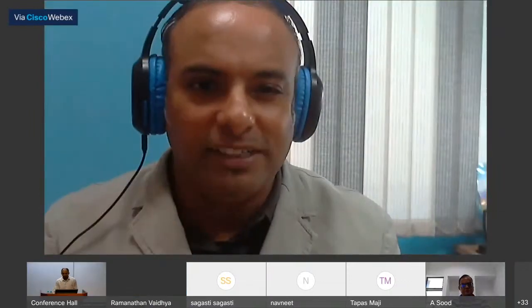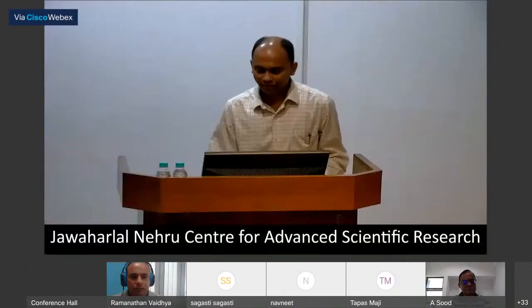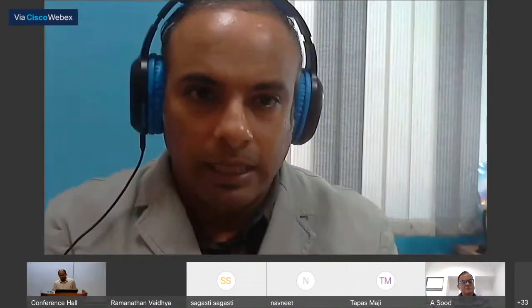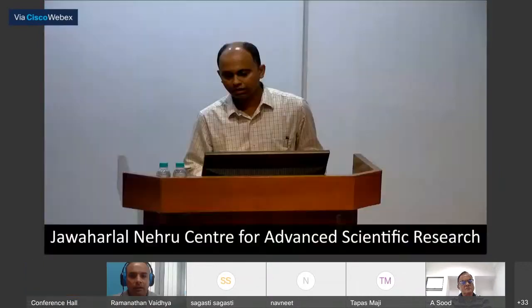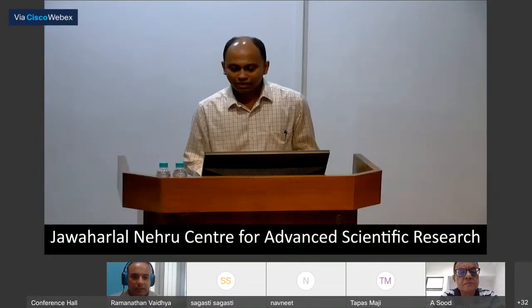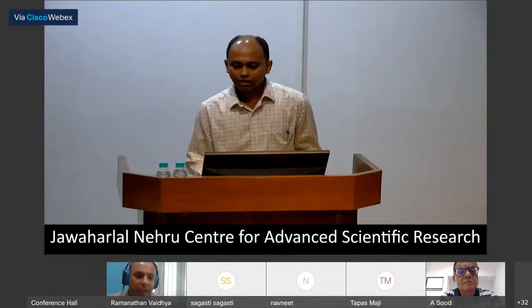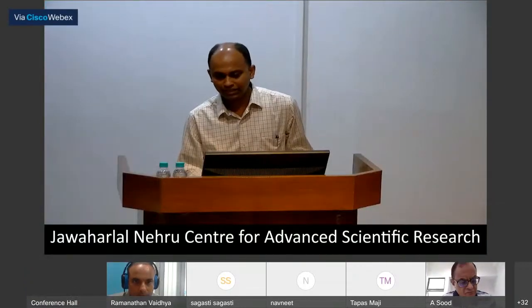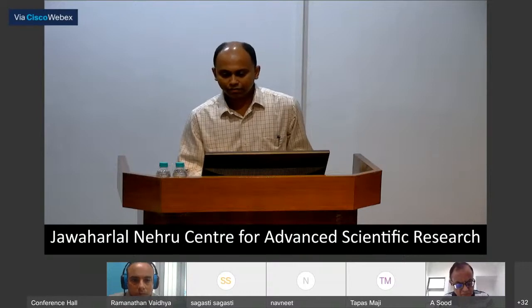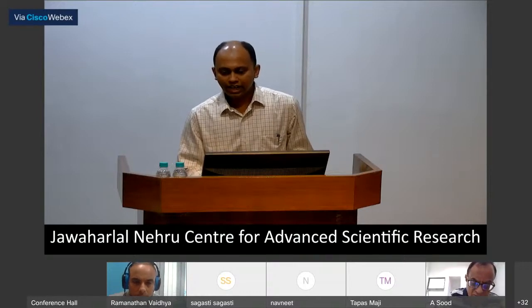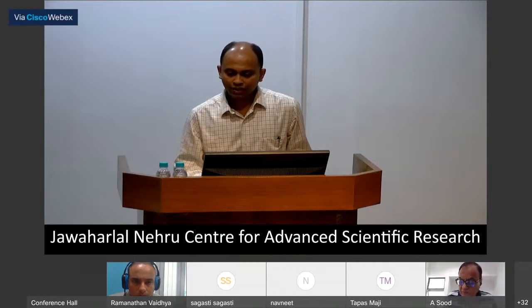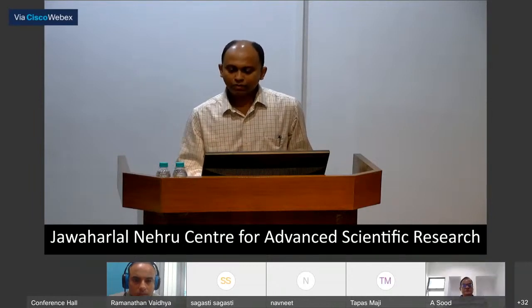I completely agree, you have convinced us, no doubt. But my question arises from the same root as what Professor Kulkarni was saying. For 6% doping, to get such a uniform ordering all across the material is a very unlikely situation. But a 6% doping can cause twinning of the crystal in such a way that you can get this. That's why I asked. This kind of nanostructured thermoelectric has been well established in the last 15 years, and these superstructure domains are actually not so well known, but nanostructuring is known, and 6% is quite high.